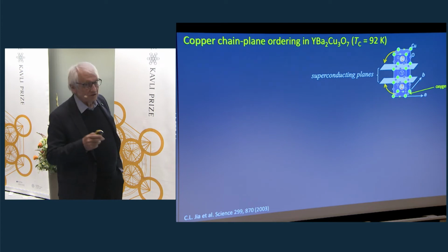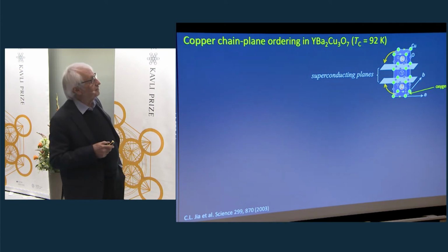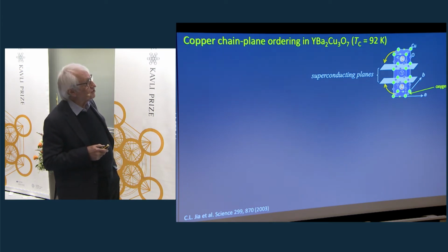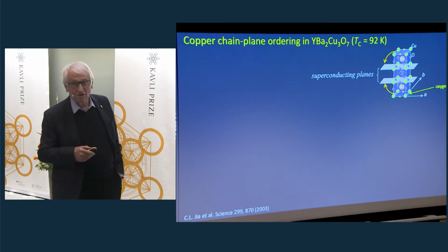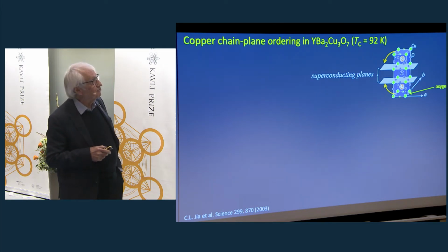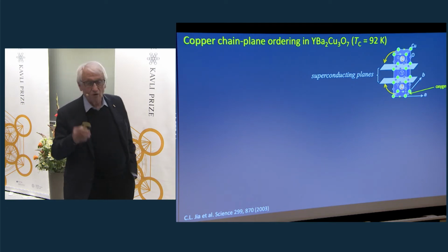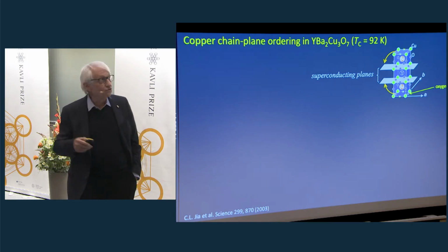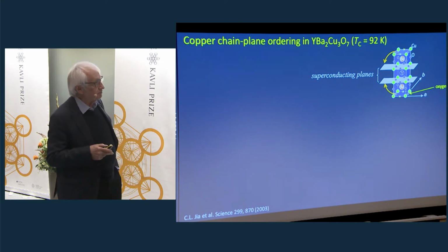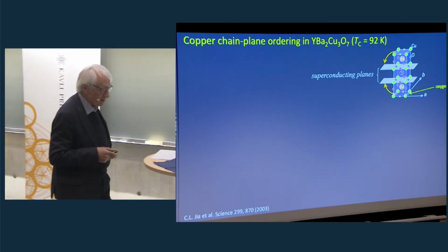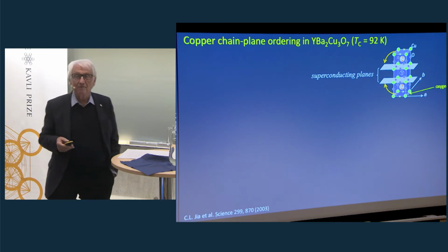So there's one important point here. You see these crosses. And the theory of high-temperature superconductivity for yttrium barium copper oxide postulates that the positions at the crosses are not occupied. There should be no oxygen atoms. And so the question was, can this be shown experimentally?